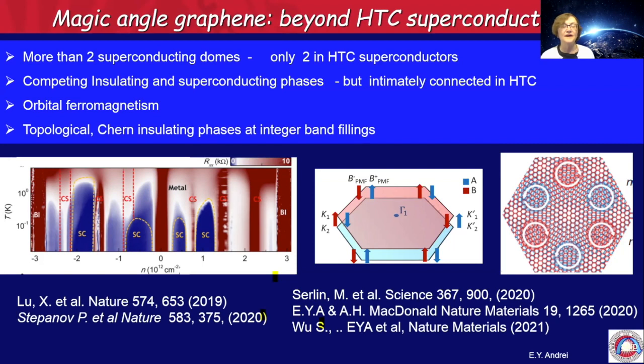So at this point, it looks like magic angle twisted bilayer graphene has many similarities with high temperature superconductors, but in fact, it is much richer. And also, it looks like it may not help us solve the mystery of the mechanism of high temperature superconductivity. It's also unlikely that it will bring us to room temperature superconductivity, but there are many, many interesting things there to explore. For example, whereas in high temperature superconductors, we have 2 domes that flank the insulating phase, it turns out that in graphene, we have many domes that flank each integer filling.